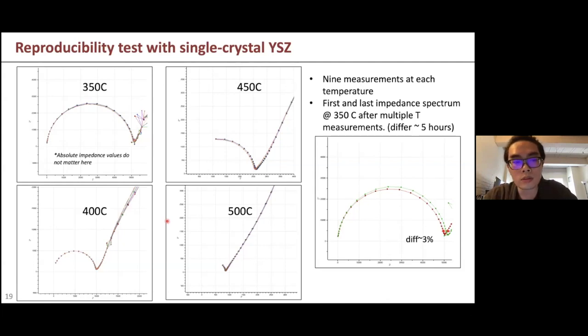So for example, on the top left, when I measure the impedance of the sample at 350 C, there are actually 9 spectra there. And you can see they almost perfectly overlap each other. Between the 9 measurements, I didn't just consecutively click my mouse button and then say, oh, my reproducibility is very high. Between different measurements, I changed the condition of the device to other conditions, and then came back to the original condition and measured the impedance again. So this shows how accurate the device can be, and also the reproducibility of the measurement.